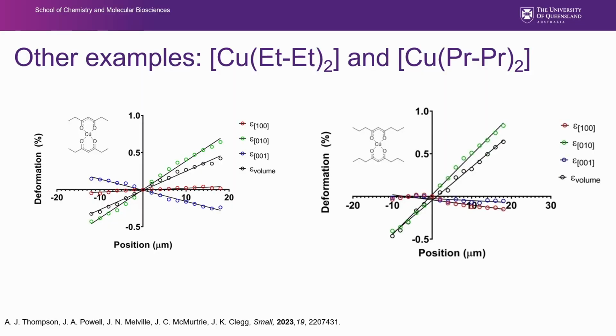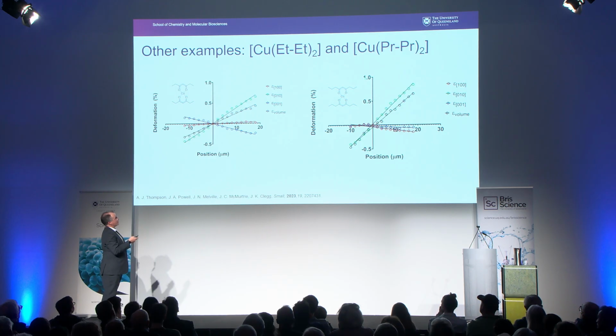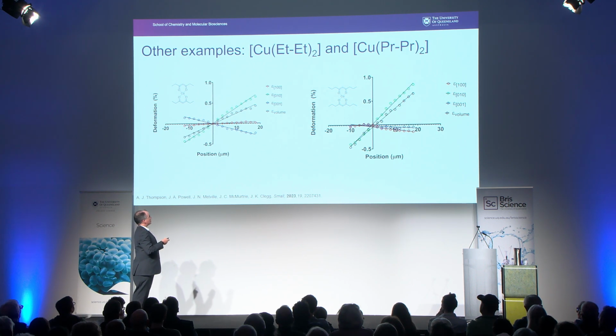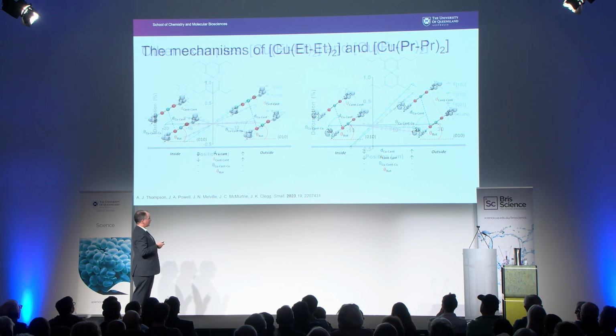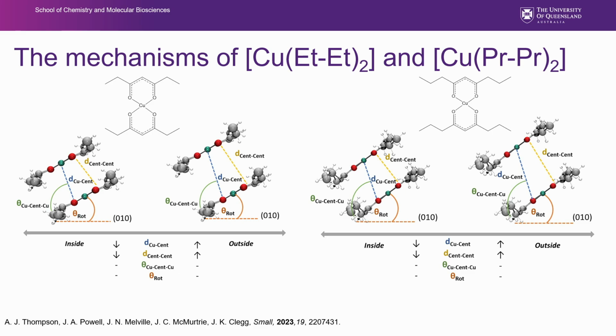So we can do this with lots of our other crystals, and this is just to highlight that they're not all the same. Everything works differently. Here we've just changed a methyl group to an ethyl group, and here we've changed that ethyl group to a propyl group, and now you'll see that the changes in axes are all different. But again, the one thing that's consistent is these are bent elastically, and that we're getting the change nicely here in the B-axis, which in both of these cases runs up the length of the crystal from the outside to the inside. Again, instead of rotation in these, we actually start to just see the molecules drift further apart from one another, rather than rotating.